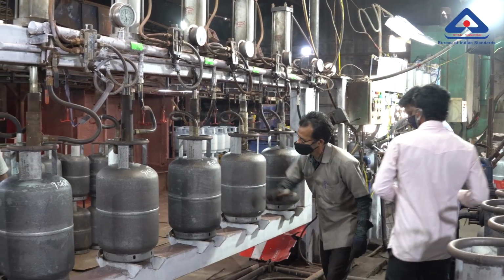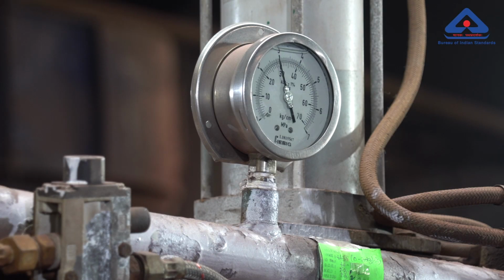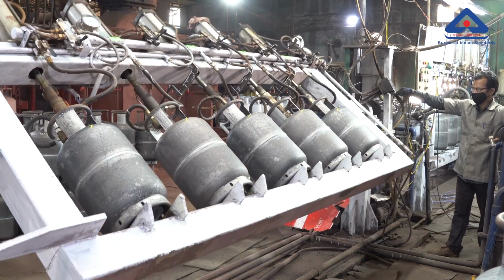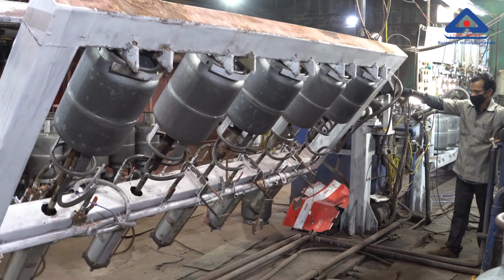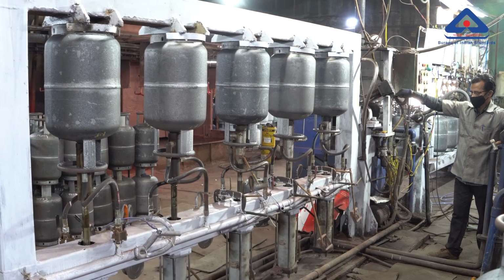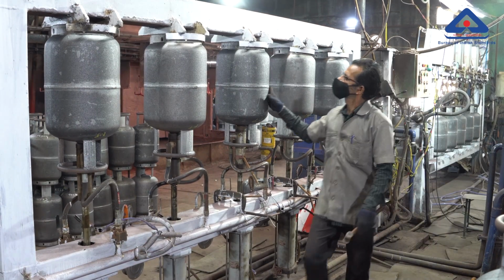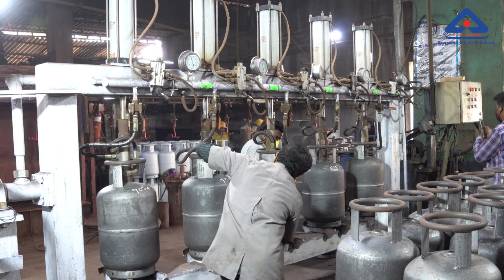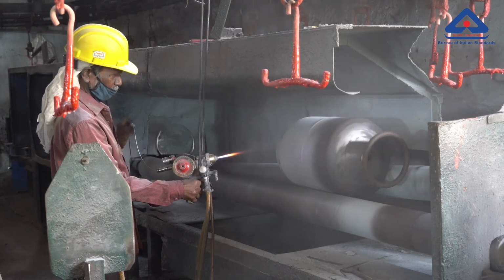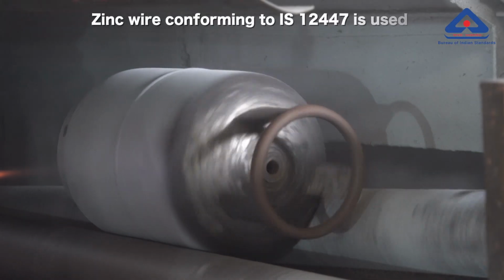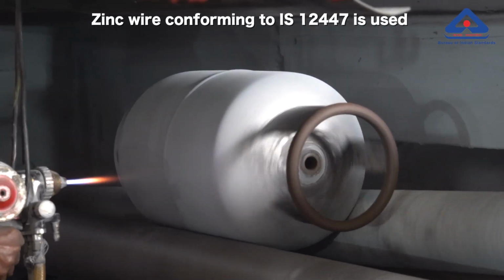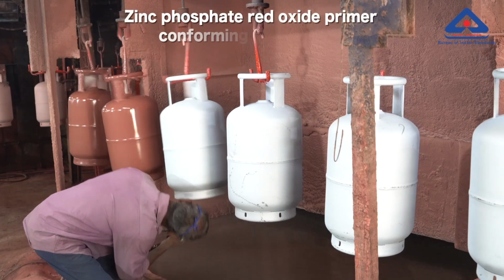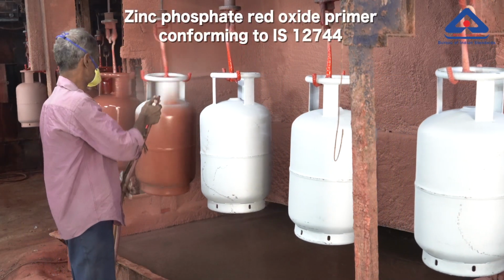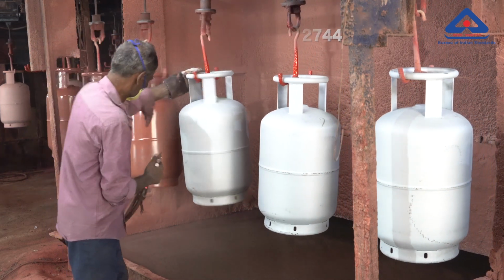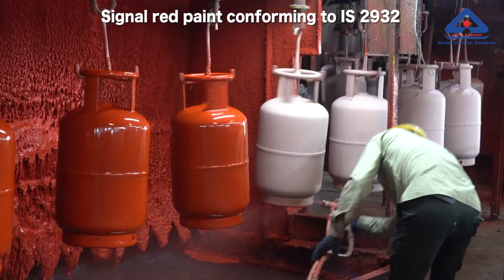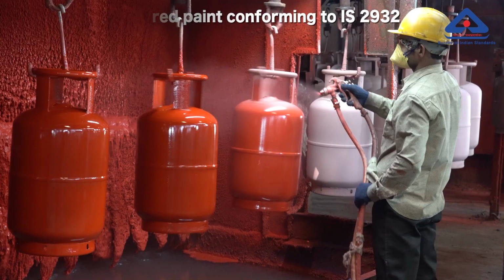Now each and every cylinder will undergo hydrostatic testing. Here, the quality of welds on the cylinders is checked by filling water at high pressure and held for 30 seconds. Every cylinder is checked for leaks, sheet cracks or any other defects. If leaks are observed, the cylinders are rejected. Cylinders passing the hydrostatic test are first coated with zinc to prevent rusting. Zinc wire conforming to IS 12447 is used in this process. Then they are coated with zinc phosphate and red oxide primer conforming to IS 12744. And final coating of the cylinders is done with signal red paint conforming to IS 2932.